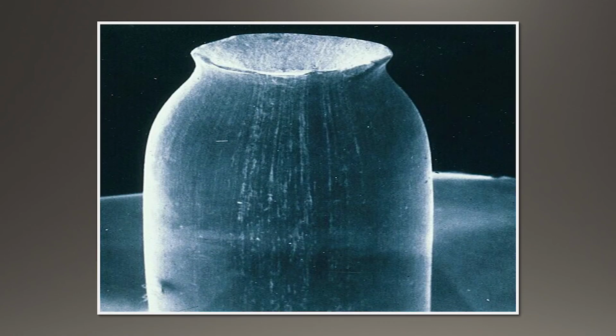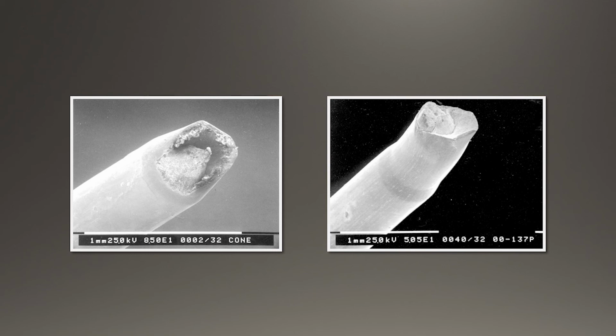This happens to be a tensile break, and there's a void. Tensile breaks usually occur in ductile materials. These voids are not the cause of the break, but they usually occur as a result of wire necking down and forming a tensile type break. Now, here's an example of a cone end of a ductile cup and cone break. Here's another sample. It looks very similar, except you can see something over here. This looks like it might be something sticking in.